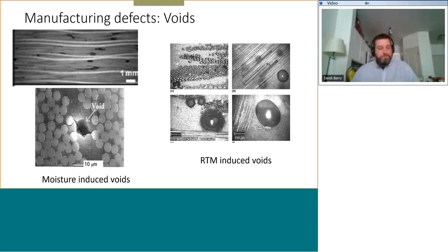Here are some pictures taken in the laboratory. You cut up the composite sections, you look under the microscope, and you see voids. To the right, you see RTM-induced voids. The lower the technology and the lower the cost of the process, generally speaking, the more defects there are. You can see the voids are much bigger than the fibers in the composite. On the left bottom, you see an example of a void trapped in the consolidation process. Even with vacuum, we're not able to draw the void out, and it's between the layers, initiating cracks that are causing debonding of the fibers.